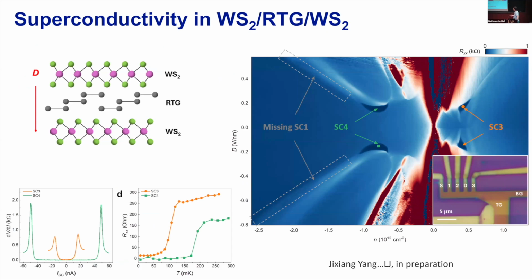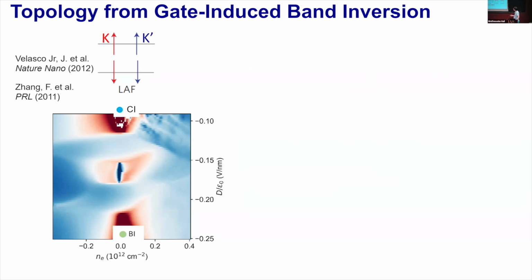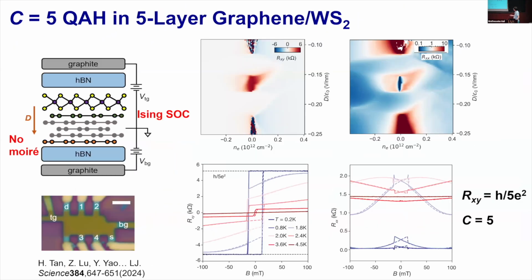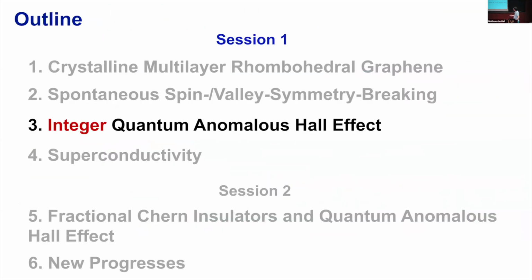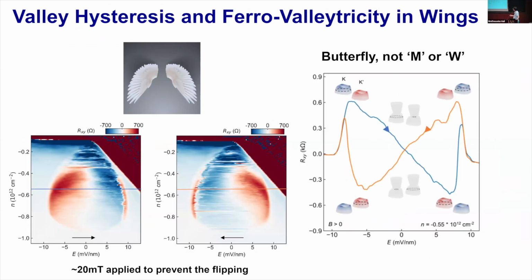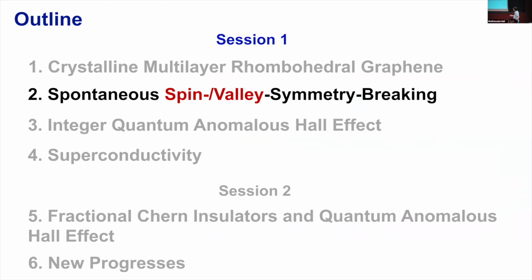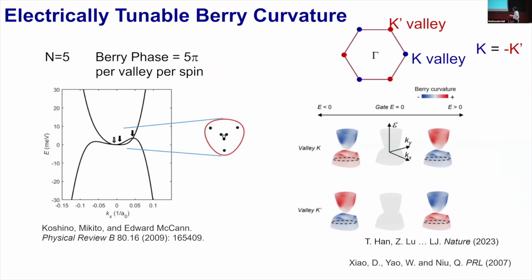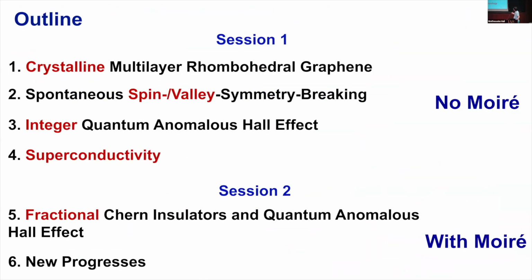I think if you look at the band structure calculation based on tight binding, that the really flat region that has some up and down, in the pentalayer graphene case, I think it's roughly in the range of probably 5 meV or smaller than that.